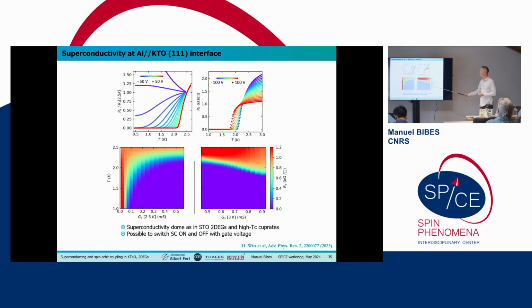So, superconductivity. Just like in the case of the STO 2DEGs, we can apply a gate voltage, and we can suppress superconductivity. These are 2 different samples. But here I've replaced the gate voltage axis by the conductivity in the normal state, and you can see that we recover this kind of dome shape behavior. And so we can certainly tune the superconductivity on or off with the gate voltage.